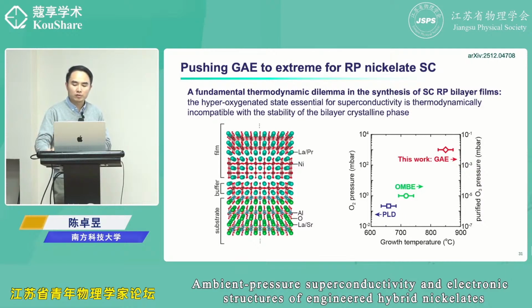First, you grow the film under a condition that's good for structural stability. You get the bilayer structure first, and it is an insulating film after you just grow it. Then you use a very aggressive post-annealing step to force the oxygen inside the lattice to make it superconducting. So that's a two-step process to decouple this conflict.